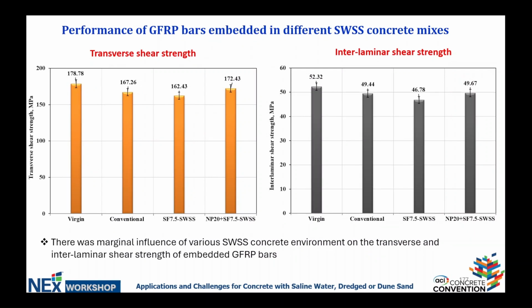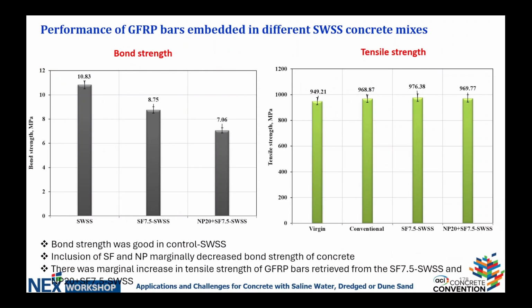Then looking at the GFRP, I repeat what many colleagues have already mentioned, and this is not really the topic of today, but what is important to state is that even though we have demonstrated the durability of GFRP in particular, which is the focus of this project, under conventional concrete mixtures, there is really no major difference if you add seawater or sea sand to the mixture. The only area where there could be some slight difference is in the bondability of the concrete. This is a property of the concrete, not really related to the GFRP itself. So being cognizant of that, this might have an impact on some of your parameters such as development length, but I don't think this is an issue. If you expose the bars to this more aggressive environment, in terms of tensile strength, you don't see a difference.